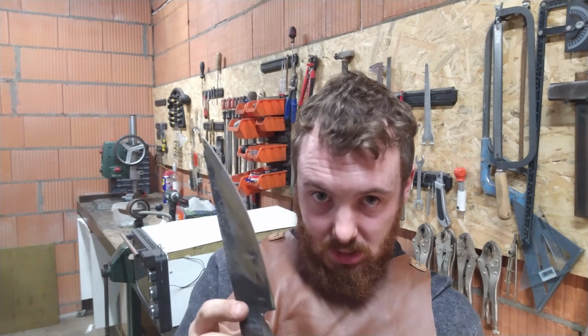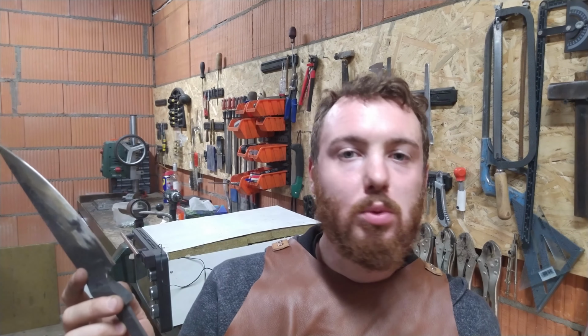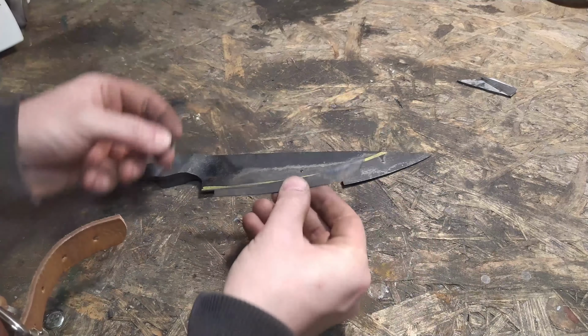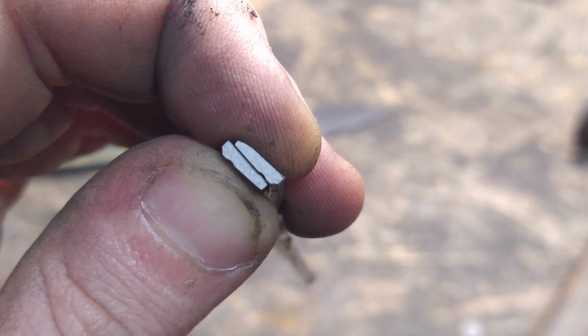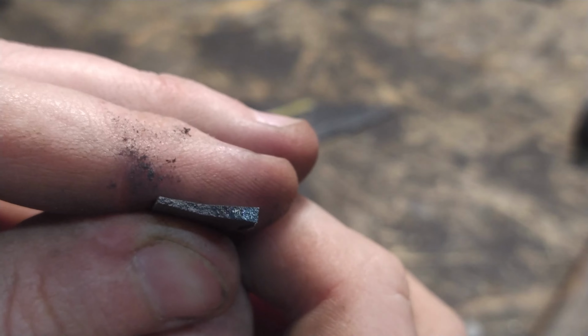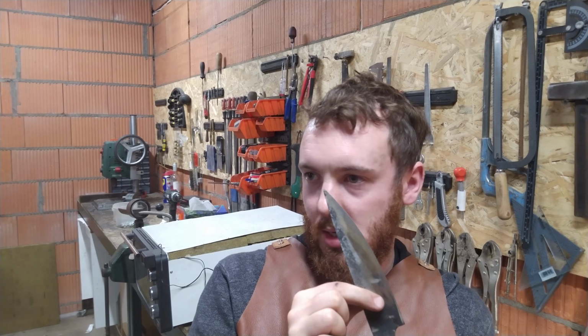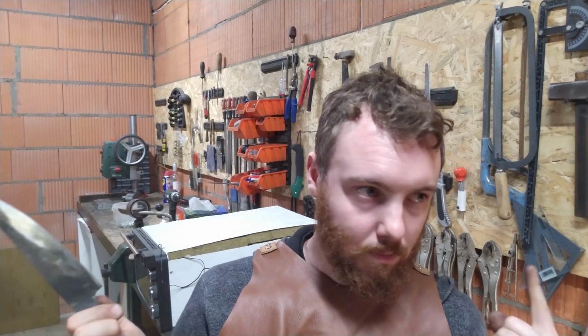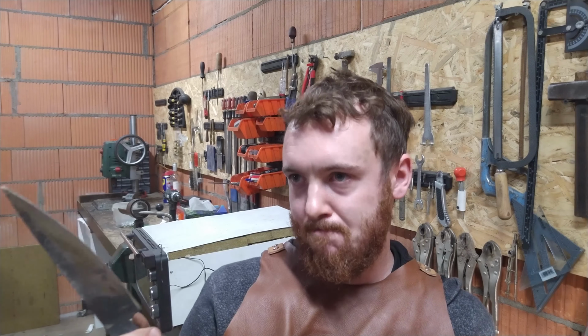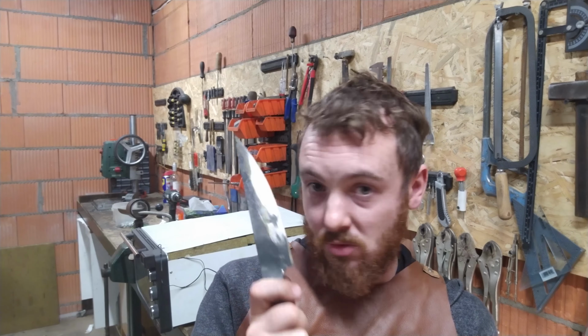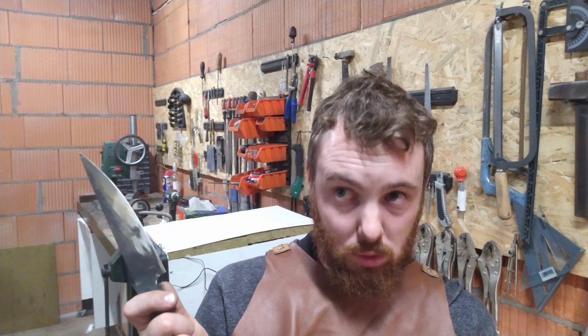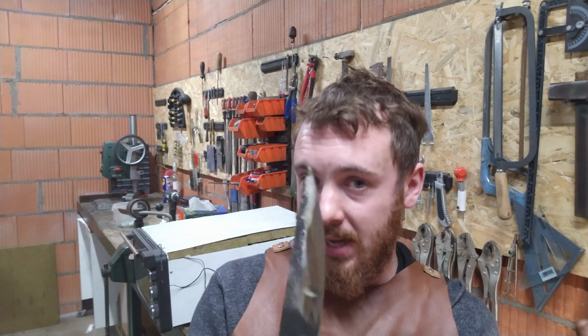But what is interesting, and I will focus on that, sorry this will be boring, is that the grain structure on the heel is significantly better, still not perfect, but significantly better than on the tip. And if I can confirm that this part is super duper bad with the hardness tester, and this part is significantly better with the hardness tester, that means that I can use the hardness tester as a tool to verify the grain structure without making a breaking test. And this is, I would say, super valuable, because right now every time I do some grain structure breaking test, just to be sure that, you know, the knife is well made.